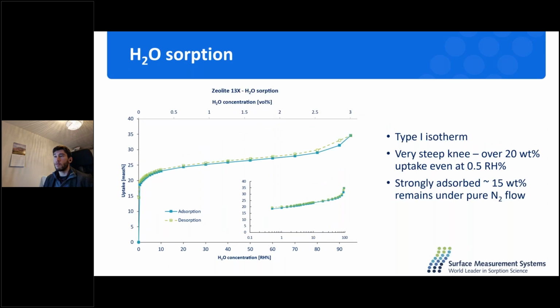Let's look also at the water isotherm. Now, the water isotherm is definitely a type 1, with a very, very steep knee here at low concentration. So what we see is that even at 0.5% relative humidity, which means a very, very low relative humidity, this material takes up 20%, or nearly 20%, in water. The water really strongly adsorbs. There is a very high affinity between water and the zeolite 13X.